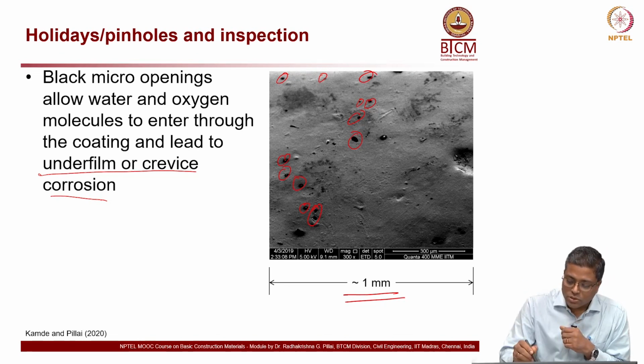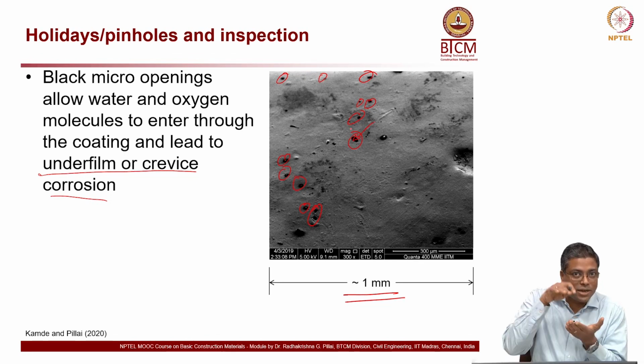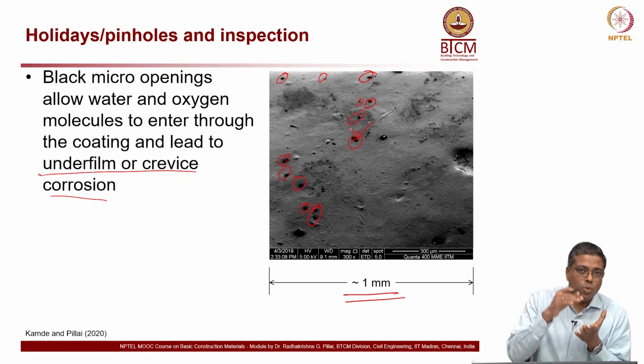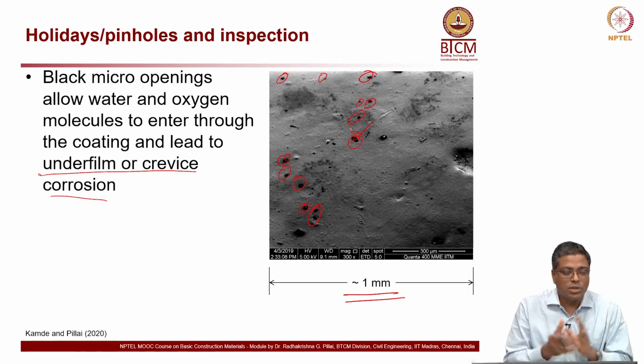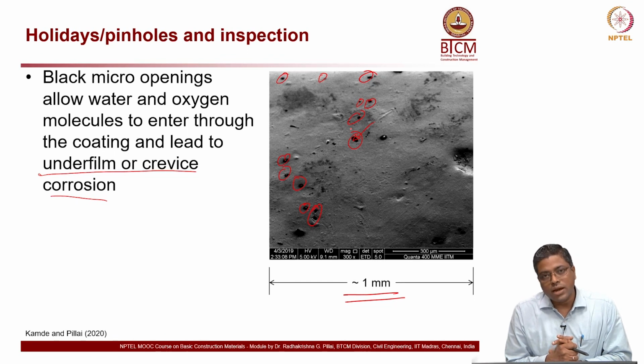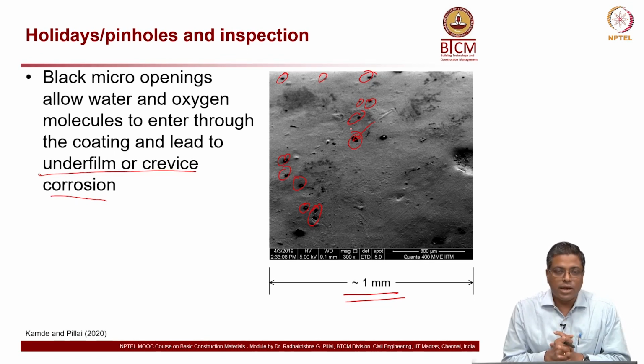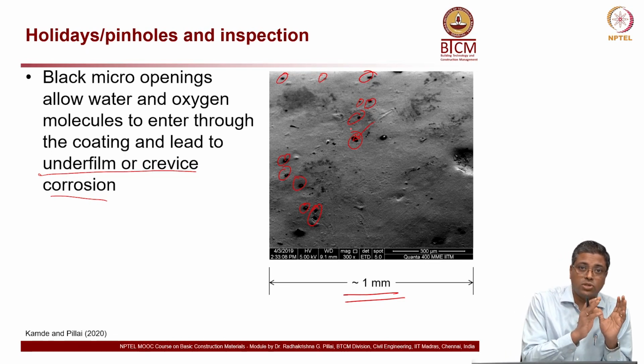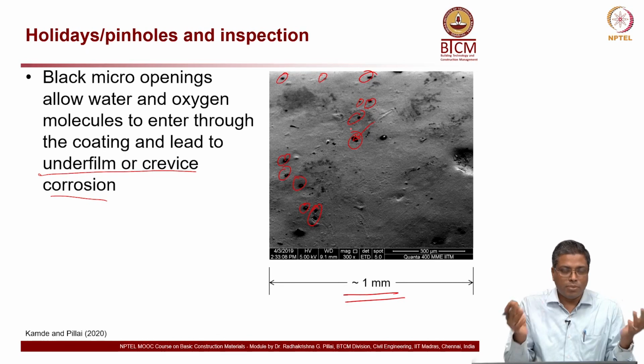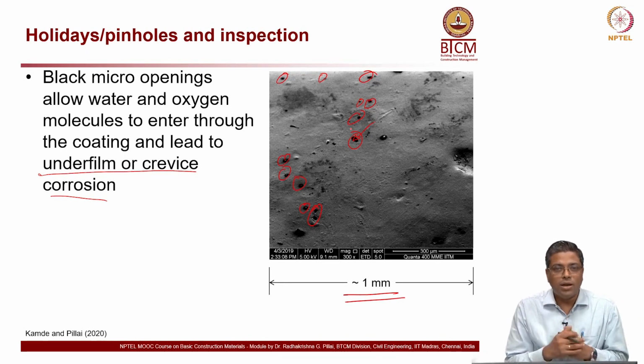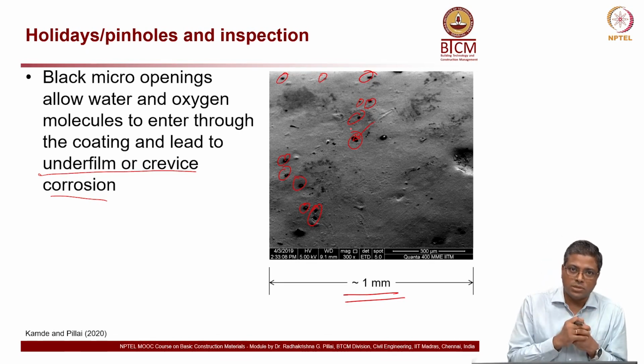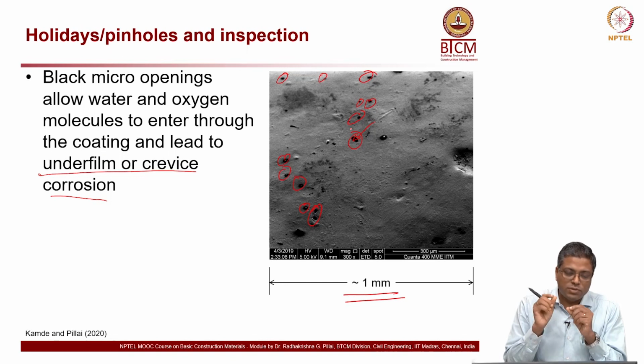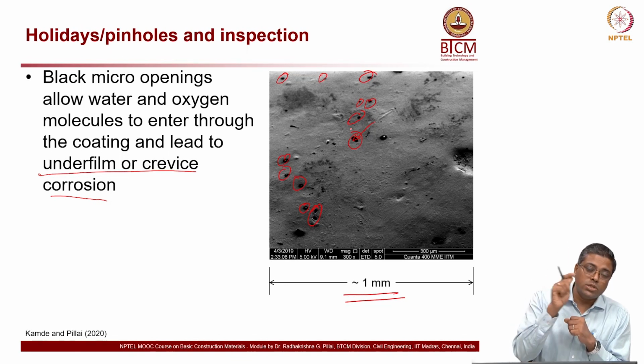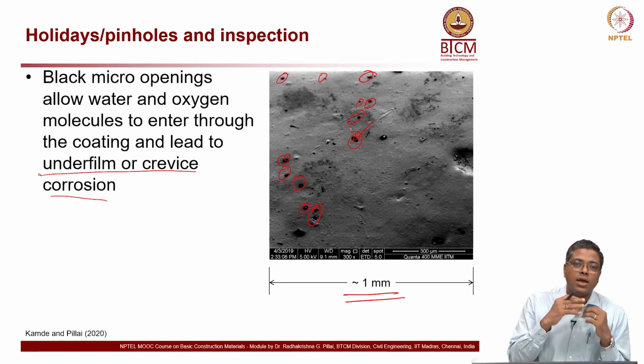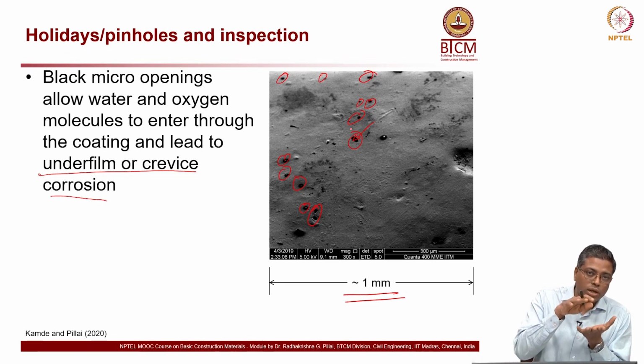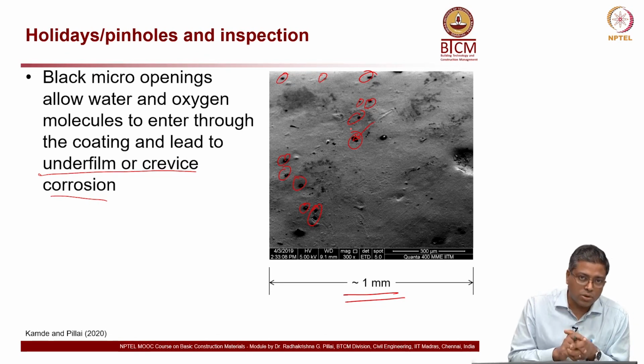molecules can go through. They can go through all these pinholes and reach the steel beneath, right? Once they get inside, they get trapped, and then crevice corrosion can happen. Let's not go into more detail on that, but I am trying to show you an example which you can very easily see when you look around a metal gate at your home or a window grill where you have applied paint, but you still see blisters, because there are very fine pores available on the paint surface through which moisture and oxygen can penetrate, and they will get trapped in between the coating or paint and the steel surface, and then it will start corroding.